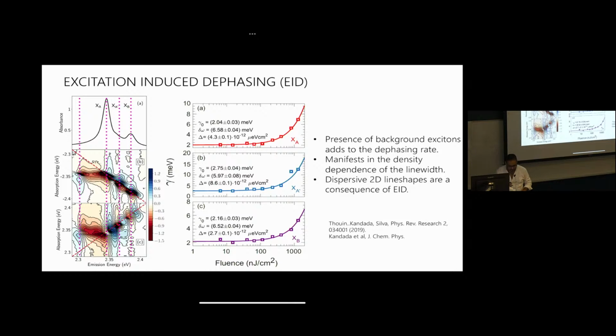So you get also a lot of information through line shapes. Without really getting into too much detail, because now we're starting to get into the more involved nonlinear spectroscopy, the line shape has very clear signatures of this excitation-induced dephasing at very early time. You measure the real and imaginary components of your spectrum, essentially of your permittivity function, and you should expect an absorptive and dispersive part, but they're mixed because of these nonlinear many-body interactions. And when that dissipates, because the scattering rate is very important, at early time you wait a few, to us a very long time, a few hundred femtoseconds, and all of a sudden you no longer feel all of these Coulomb interactions, and now your line shape looks like you would expect from the textbook. And so that's important.